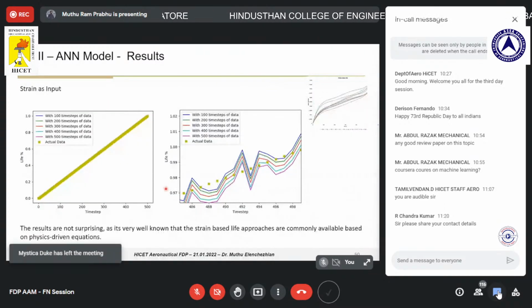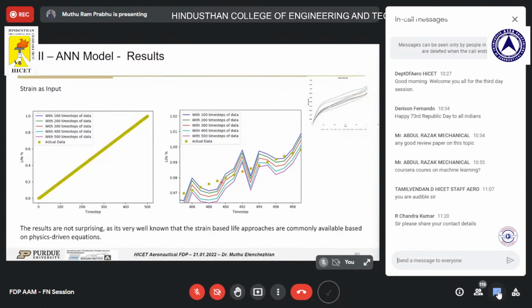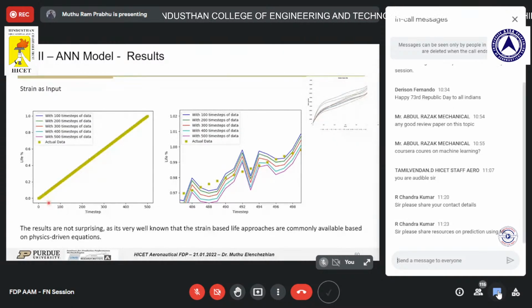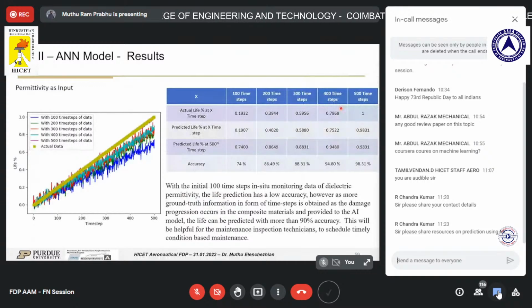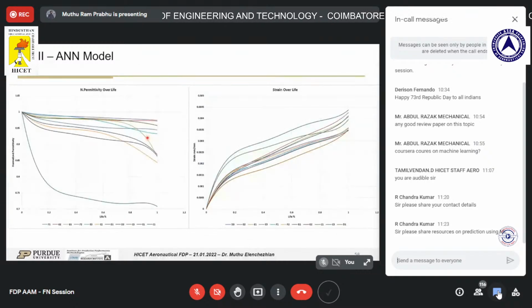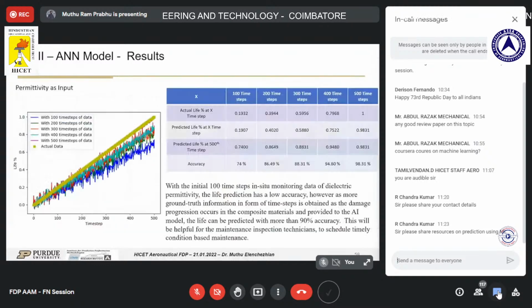But this was not the case with strain, because the strain data was very close to each other for all the different time steps, even when you have more data. So with the strain data, we were able to get closer predictions because the strain data had a uniform behavior, but the dielectric data did not have a uniform behavior in the overall response.